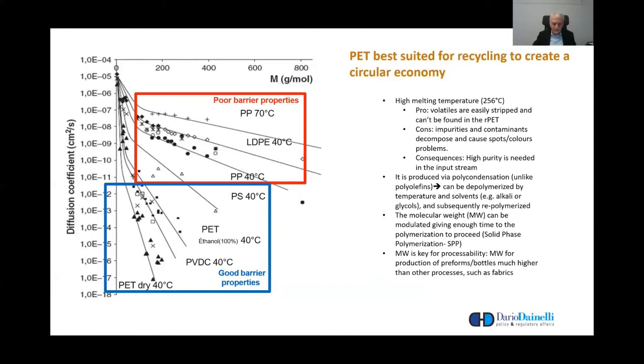On the other hand, as temperatures rise to strip out volatiles, impurities and contaminants might decompose and might cause problems relative to spots, colors, and burns, and other kinds of undesired contamination. That's why high purity is needed in the input stream, and the better the collection, the better is the quality of the final RPET. PET, unlike polyolefins, is produced via polycondensation. That means that it can be depolymerized by temperature and also by solvents, and subsequently it can be repolymerized.